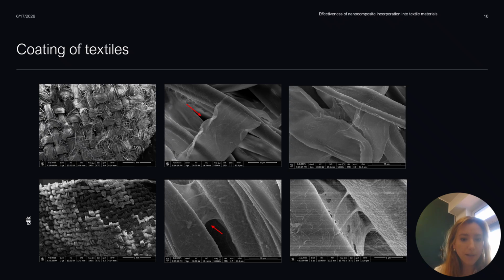Here, the micrographs reveal graphene oxide sheets spanning between textile fibers, as highlighted here by those red arrows. In some areas, the nanocomposite also wrapped around individual fibers, confirming successful incorporation and the good interaction of the nanocomposite with both cotton and silk material. Following the successful incorporation of the nanocomposite into the textile structure, an important question emerged. How stable would these functionalized materials be during practical use?